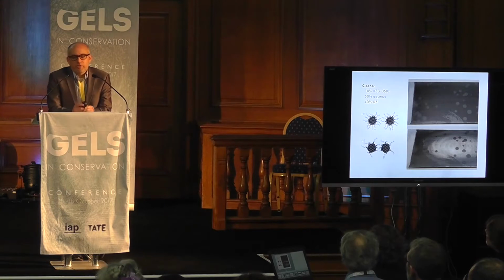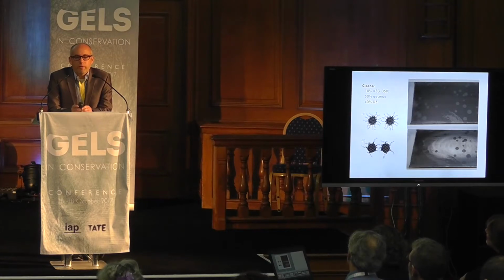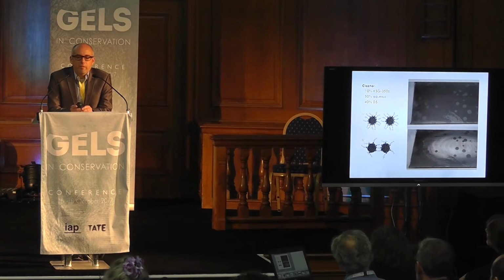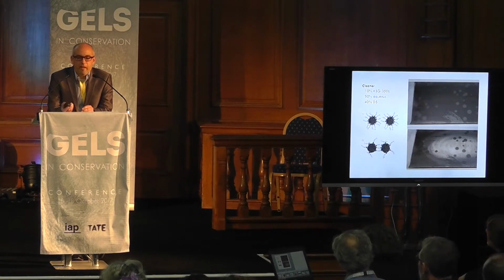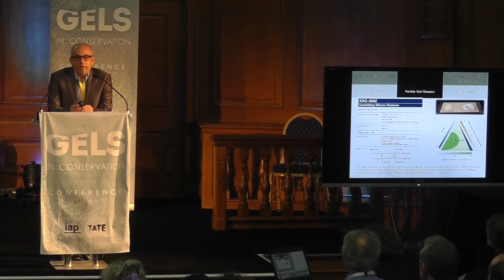So like Richard said when he started out, we went down a river and we had to turn back from this river. We went down this path with these particle cleaning emulsions, and we realized that they're not strong enough. We built them around things that we know, these D5 cyclomethicones and the KSG particle emulsifier. We started out with many different particle emulsifiers, and the right aqueous cleaning conditions to minimize swelling and minimize extractives in these paint films. But you can see we can clean those unassociated soils at the surface, but deeper, we can't remove those associated soils. We have to devise a cleaning system that takes that association into account. And so that became quite a thing to do.